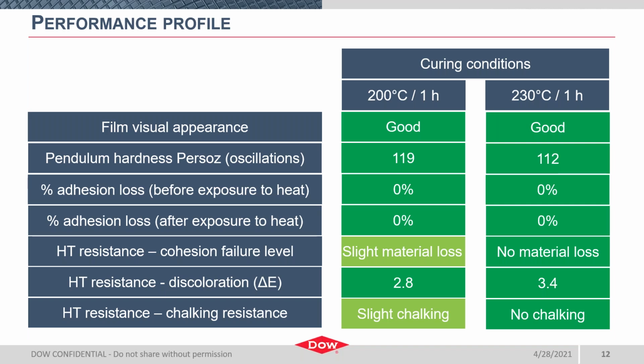So looking at the table summary, the visual appearance of the film was excellent regardless of the curing conditions, and the pendulum hardness in both cases was slightly over 100, which is very typical for a high temperature paint. The adhesion before and after exposure to heat, again, as measured by that loss of material, was excellent and really independent of cure temperature. We also witnessed very low discoloration. A delta E of about 2 is said to be detectable by the average human eye. And of course, this is going to vary greatly from person to person, but we're just over that detectable limit. I'm going to show you what that looks like on the next slide. But finally, the chalking resistance of the film was excellent, again, regardless of cure temperature in this case.